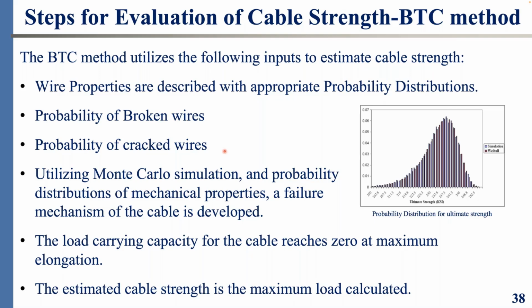We use Monte Carlo simulation to develop the stress strain curves for the entire number of wires in the bridge cable, and the probability distributions we talked about a minute ago, and all that to develop a failure mechanism of the entire cable, in which the load carrying capacity of the cable reaches 0 at maximum elongation, and the maximum load calculated is the estimated cable strength. This is in a nutshell the process.